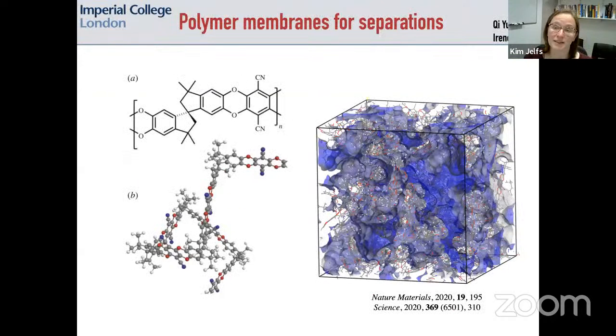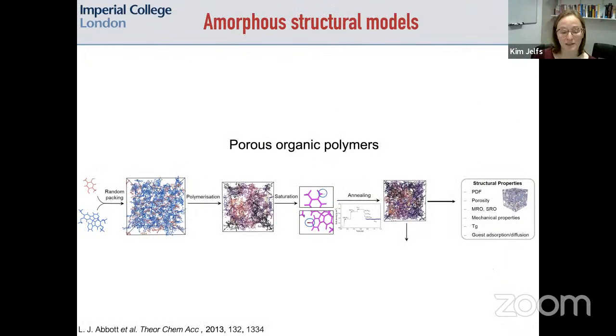Where we've done work in this area has mostly been looking at polymers of intrinsic microporosity. These were originally developed in particular by Neil McKeown at the University of Edinburgh. Perhaps in this crowd people are already familiar with these, but the basic idea is you form polymer chains that are quite contorted and are unable to pack efficiently, and so you end up with the sort of porosity that we see on the right-hand side. We use a similar approach, and here is the reference at the bottom for Polymatic, which we adapted to our purposes for both the MOFs and polymers here.